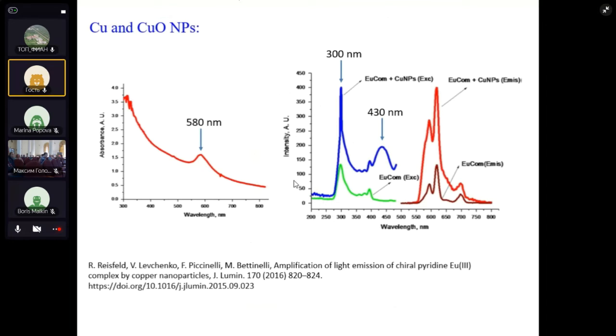And finally, the last part of my talk concerned more recent theoretical results. Again, experimental results from the group of Professor Reisfeld, but not using gold or silver nanoparticles, but using copper nanoparticles. And in this case, it is known that the plasmon band of copper nanoparticles lies much lower in energy than the plasmon band of silver nanoparticles. But anyway, they could see an enhancement factor of about 3 in this system.